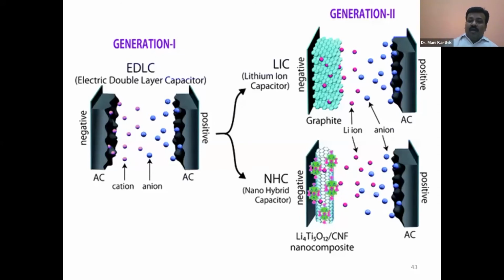But graphite has a problem, SEI layer formation. SEI means solid electrolyte interphase, and it is a very big issue in battery chemistry. If you use graphite, more layer is forming, so your voltage window is high, but the lifetime is less. But if you see LTO, lithium titanate, it's a mixture with carbon nanofibers or any carbon for conductivity, because in order to increase the electrical conductivity of LTO, we can have some composite material. With this LTO chemistry, we can only go to less voltage, maximum 2.2 volts, but you can have long stability because there is no SEI layer formation, since LTO lithium intercalation is above 1 volt, particularly 1.55, so above 1 volt. So this combination of LTO and activated carbon really gives a long cycle life.